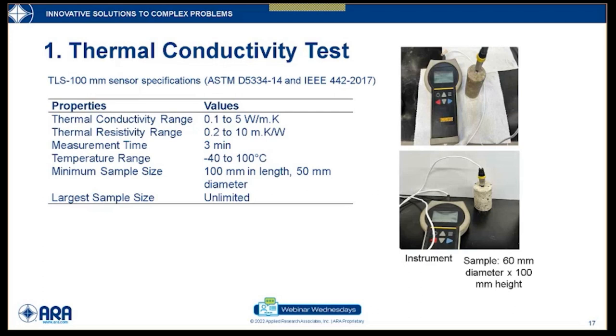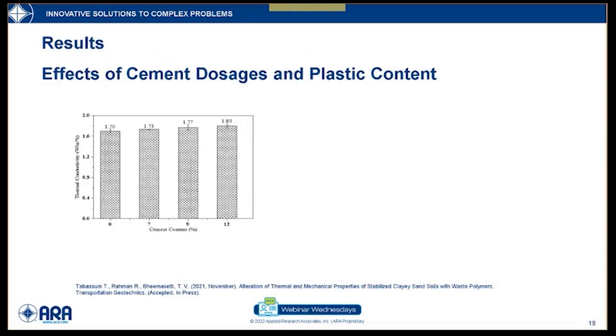This test was performed on all of the mix designs, and the results show that when the soil sample has no cement content, it is 0% cement, the thermal conductivity is a little bit lower than when cement content is added to it. So as the cement content increases from 0 to 12%, the thermal conductivity of the soil sample increases. This is due to the density of the soil sample mixture. The cement content increases the density of the soil sample, and there is more particle to particle contact in between the soil, and there is more flow path for the heat to flow. So due to the increase in density, the soil thermal conductivity increases because there is more particle to particle contact.